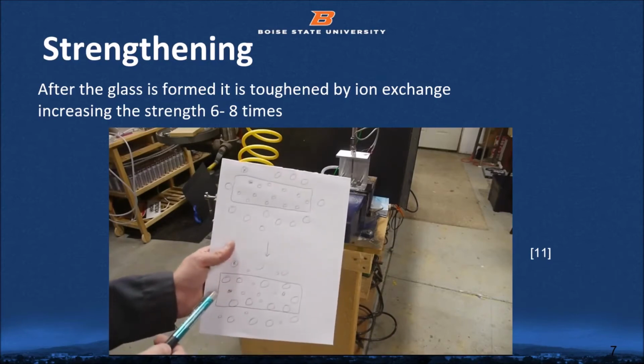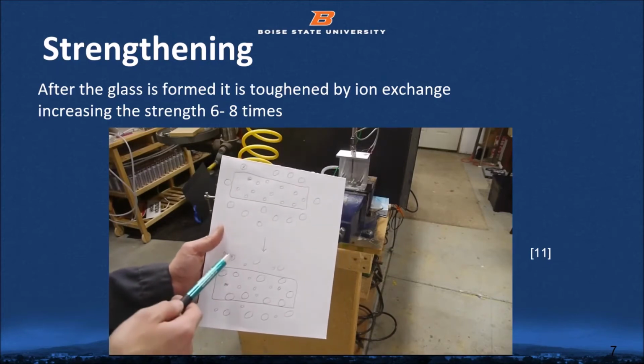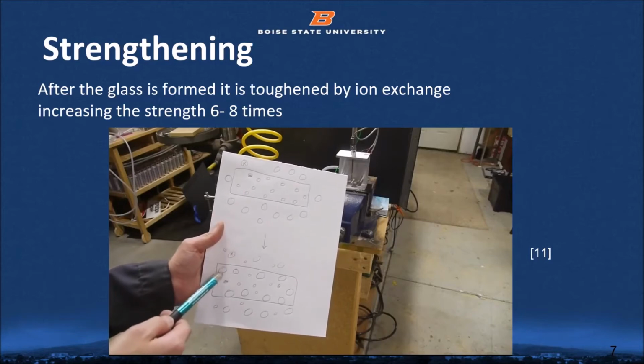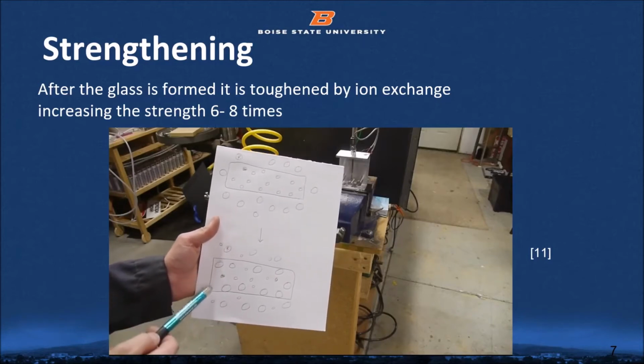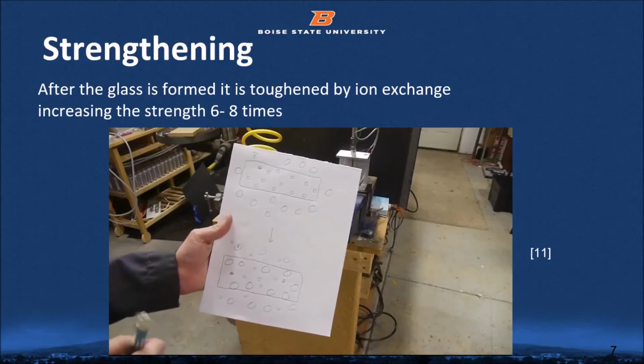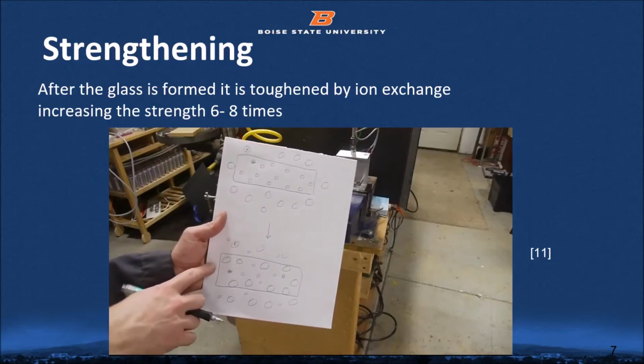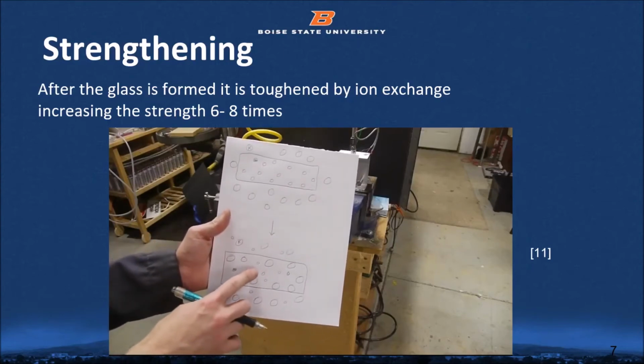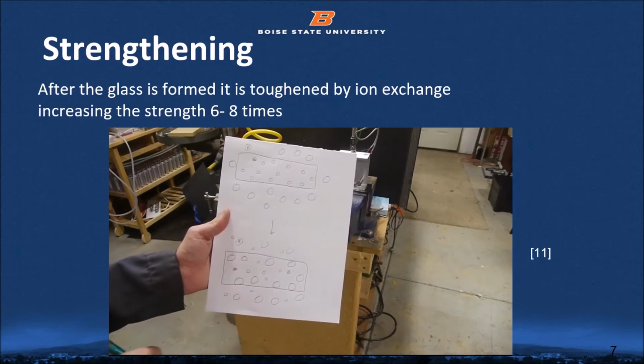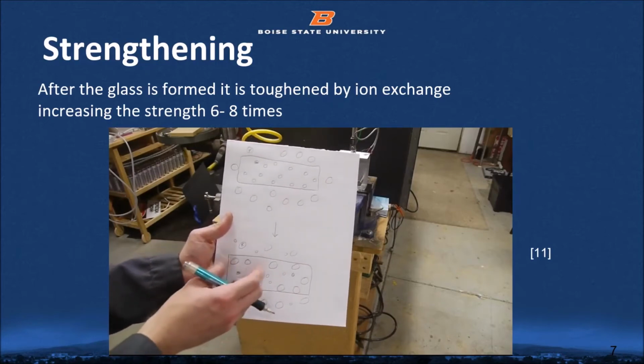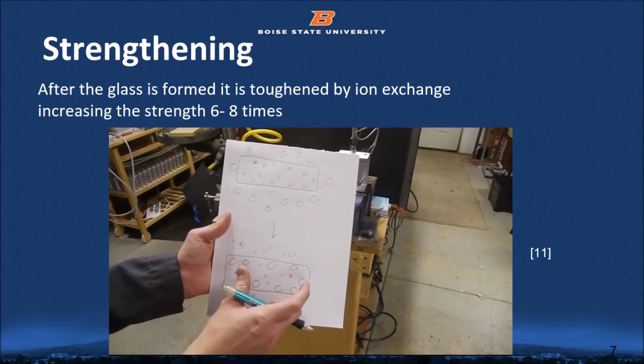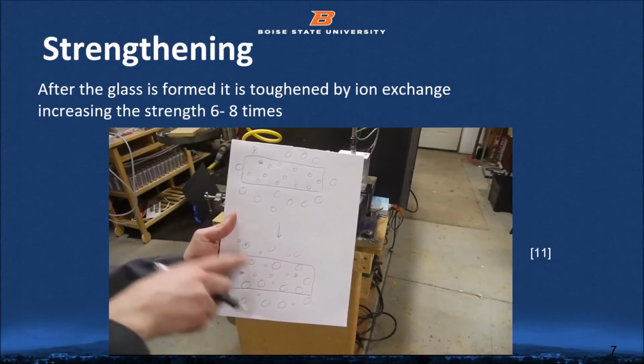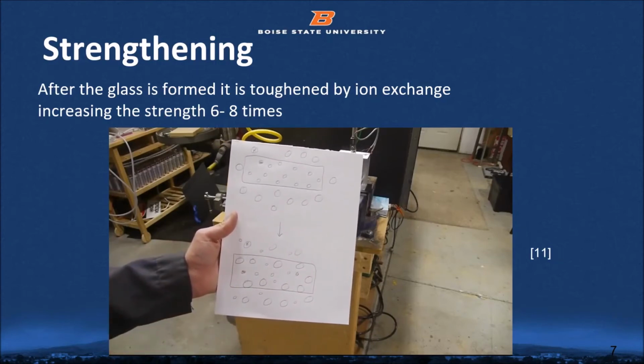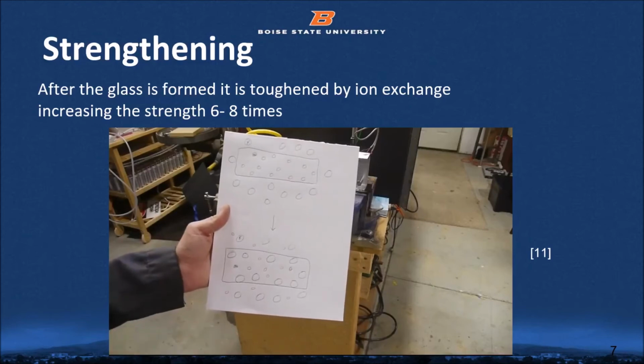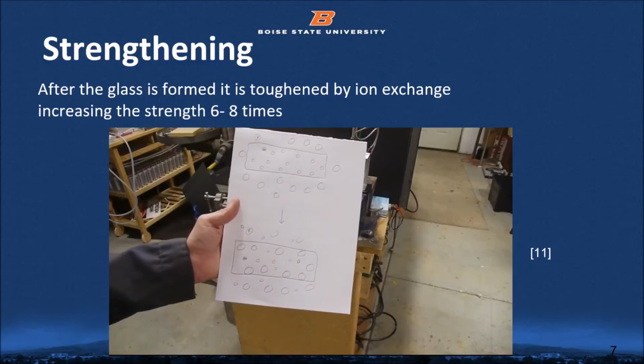And through the natural process of diffusion, some of the potassium atoms will take the place of the sodium atoms in the piece of glass. So what's happening here is these larger potassium atoms are being shoved into the spaces where there used to be just a very small sodium atom. And the effect is that we've basically put the glass in compression by jamming these larger atoms inside of it. Now this process happens at a temperature lower than the glass softening point.